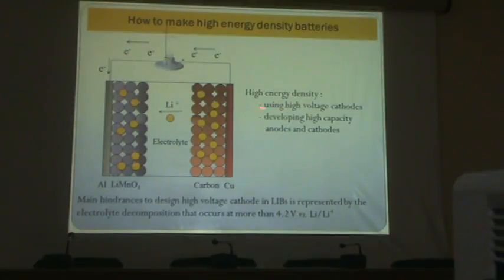What is preventing me from finding high voltage cathodes is nothing but the decomposition potential of the electrolyte, which is around 4.2 volts. The electrolyte starts decomposing at those potentials and you start getting deposition of lithium. So that prevents me from making high voltage cathodes. Why not start developing ionic liquids or other kinds of electrolytes so that I can improve my cathode performance? But that's a different kind of research. It takes 2 steps. So the easier way was to start developing high capacity anodes.